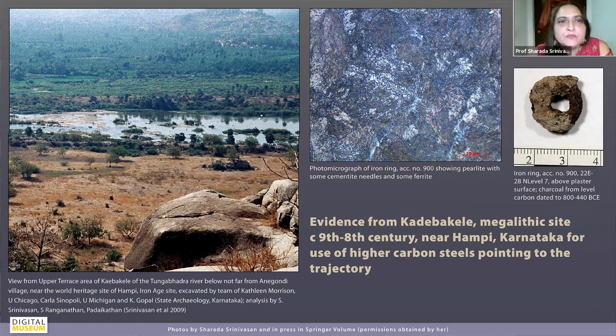And I also thought I'd point to the evidence from an earlier megalithic site, which is Kadebakele, near Hampi in Karnataka, where this site is quite well dated and excavated by the team of Kathleen Morrison and Carla Sinopoli from University of Chicago and University of Michigan, along with the State Archaeology of Karnataka. And I had done some of the analysis of the metal from the ferrous remnants. And you can see here the upper terrace area of Kadebakele, which is not far from Hampi. And there was an iron ring here, which already shows this is a higher carbon steel of about 0.8% carbon. You can see this pearlite matrix already.